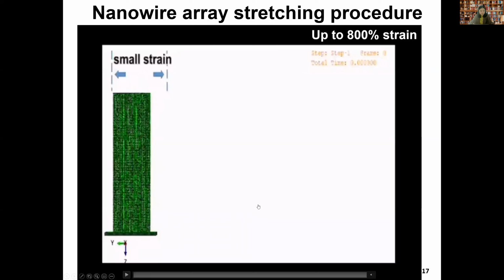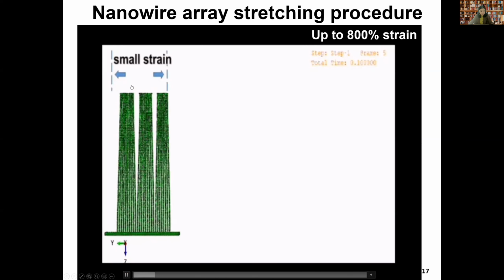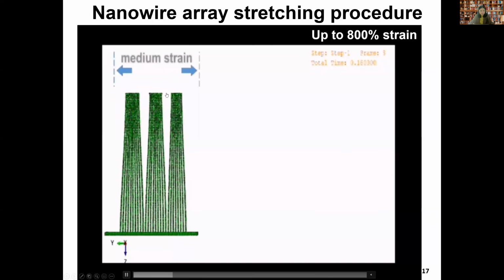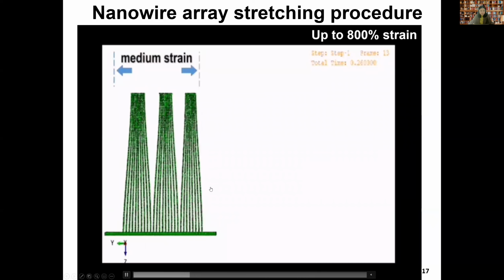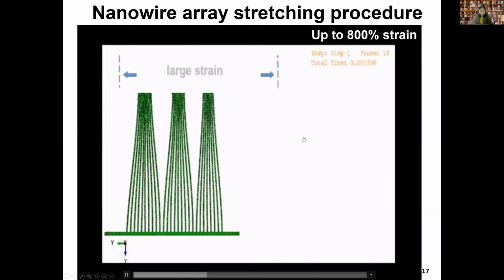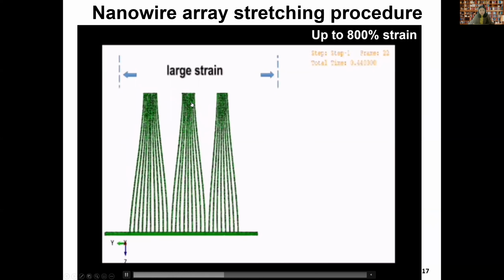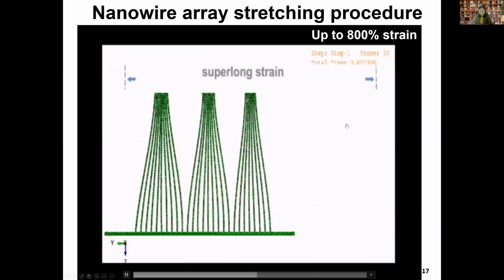This video shows the nanowire array stretching procedure. We can see the nanoparticles start to separate initially, and then the nanowires start to separate, and the V shape gets larger and larger during the process.